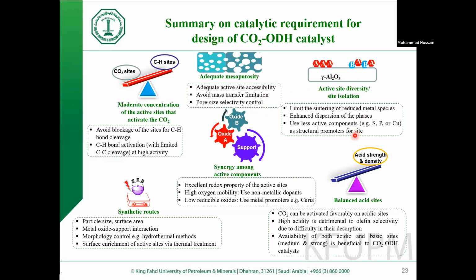Another thing that needs to be taken care of is the diversity of the active sites, because when you have active sites that are very closely dispersed, there is a possibility of agglomeration. That can be adjusted by using a promoter or modifier in order to isolate those active sites. Acidity is another important aspect. The conversion needs acidity, but too much acidity brings cracking intermediates, which are undesired.